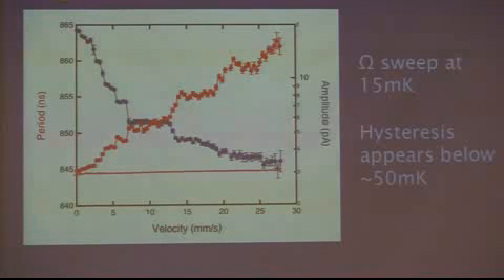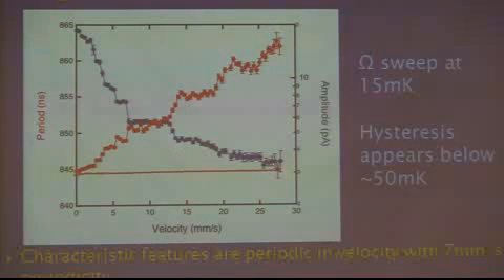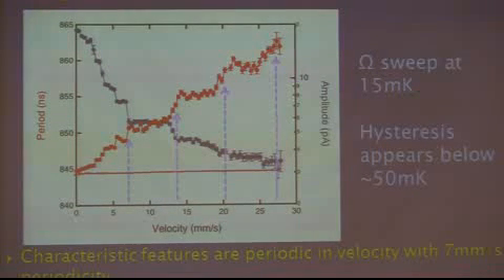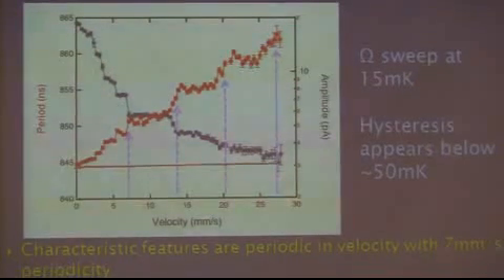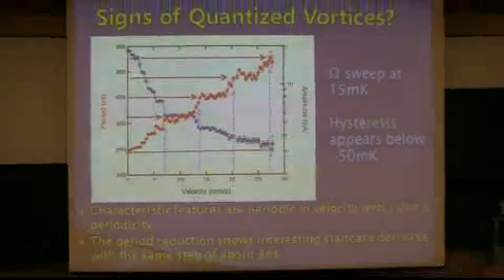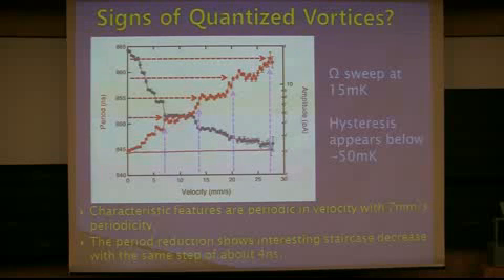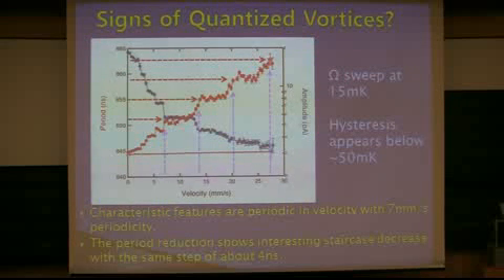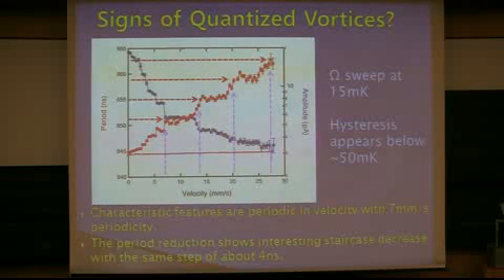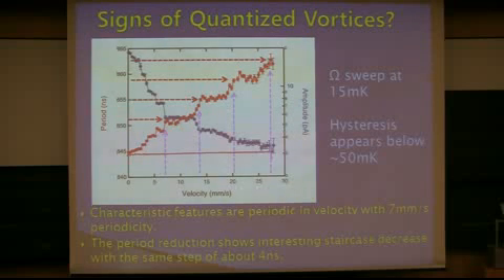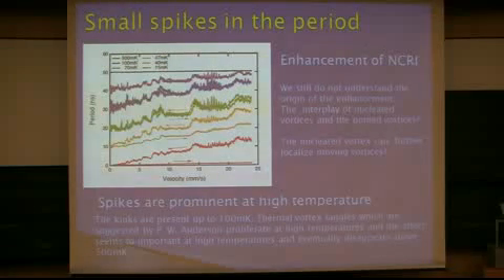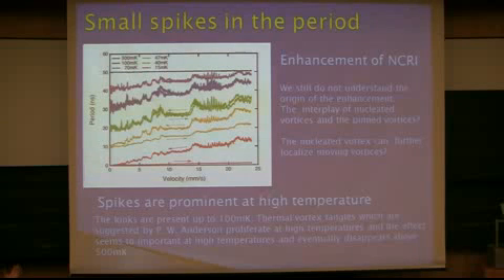Interestingly enough, the change is not monotonic. I'm the only one to find this kind of periodicity or staircase-like structures. It's very interesting. We don't really know what the origin of this kind of structure is. Maybe the existence of quantized vortices in the solid helium. I'm not quite sure, but this is a very interesting observation. That's why we systematically study this behavior at various temperatures.